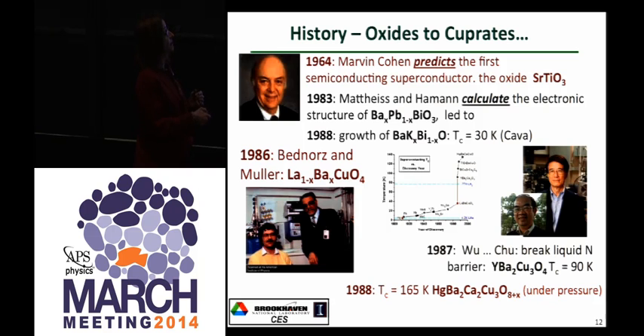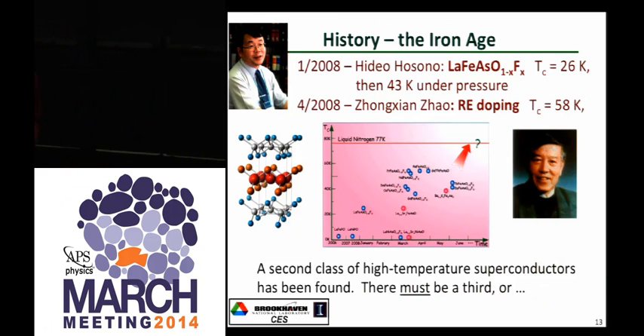And then, of course, we all know about Bednorz and Müller and their discovering of the cuprates, and Wu, Chu, and their group broke the liquid nitrogen barrier in YBCO, and the highest temperature superconductor is about 165 degrees under pressure of a mercury-based compound. So everything was quiet in the 2000s, and someone talked about, okay, superconductivity is dead, until Hosono came around and discovered a completely new class of unconventional superconductors. These were the iron-based superconductors, and that gave a real shot in the arm to the field.